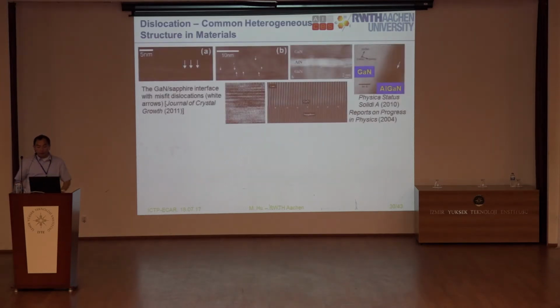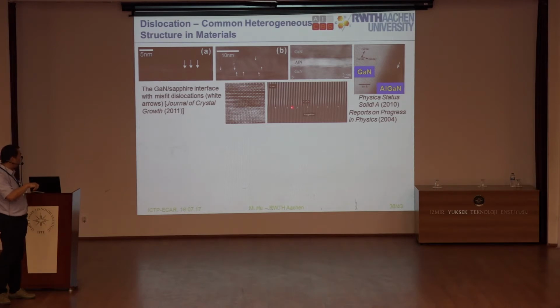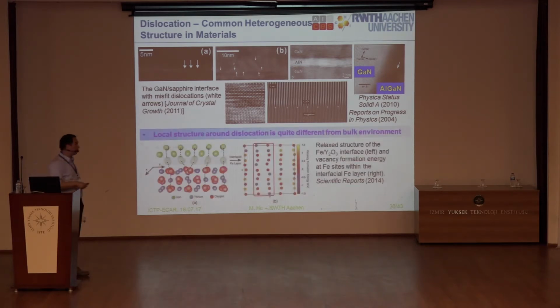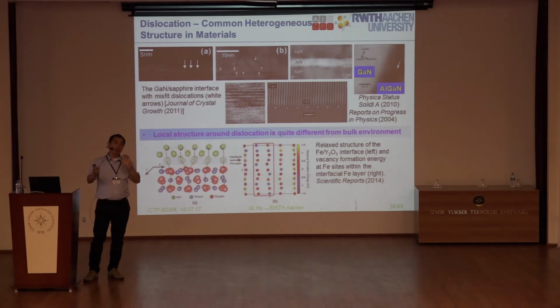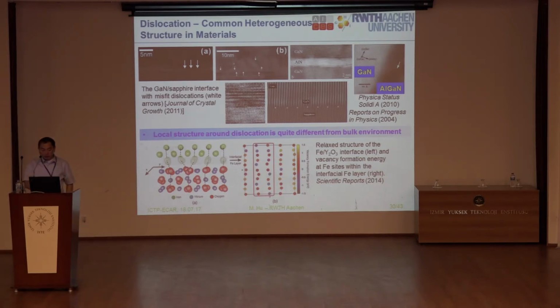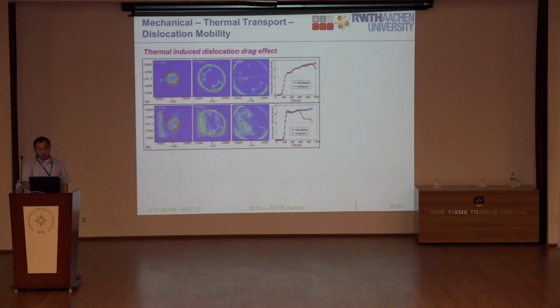So we know that dislocation is widely seen in lots of materials fabrication, especially for the gallium nitride device. So when you fabricate a gallium nitride device, most likely you will form different levels of dislocation at the interface and even inside, right? So then the question is how the phonon transport will be affected by the dislocation. We also know that in the local structure around the dislocation, you have this phonon anharmonicity because the atoms are arranged in a different way, so you have to expect the phonon anharmonicity, right? So then we use a very simple approach to study the phonon dislocation interaction.